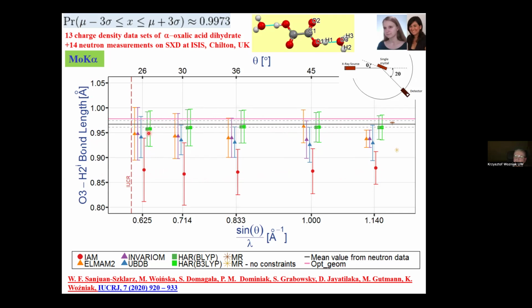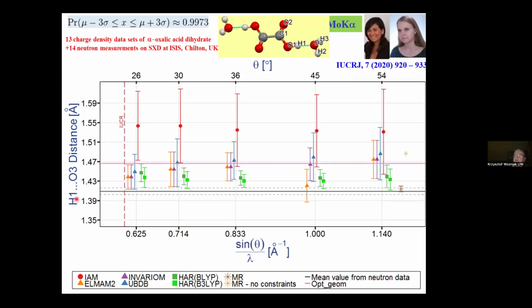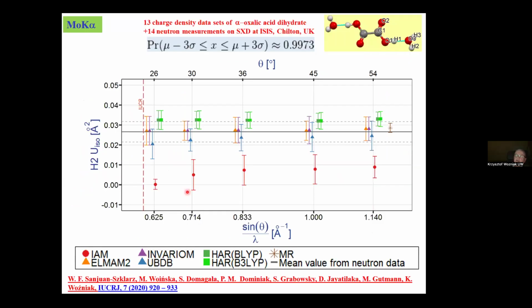And when we think about hydrogen bonding, of course, these errors associated with the position of the hydrogen atom using the independent atom model, they, in consequence, are giving us wrong distances in hydrogen bonding. But Hirshfeld atom refinement is giving very proper values, very close to neutron values of hydrogen bonding.